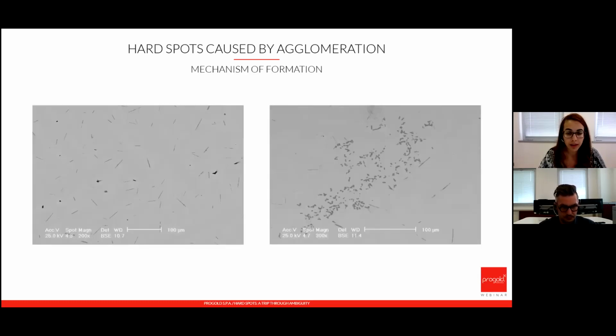So how do these hard spots form? When we start with a certain alloy, we know the initial composition. But the more we use it, the more we modify the composition of this alloy. Just think of something that has a lot of zinc in it: the more you melt it, the more the zinc is going to evaporate. But as things evaporate and their quantity goes low, it means that we are enriching the metal with some other elements.